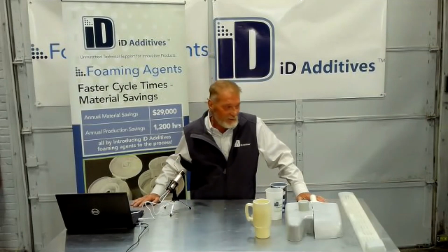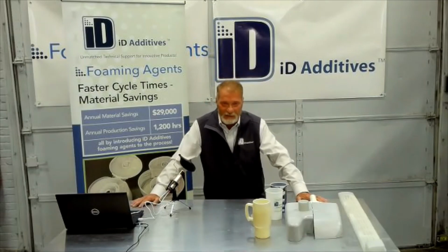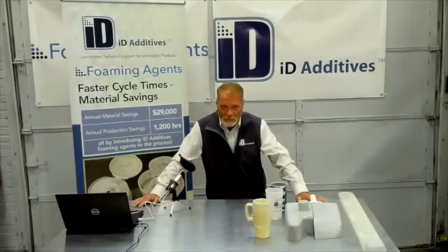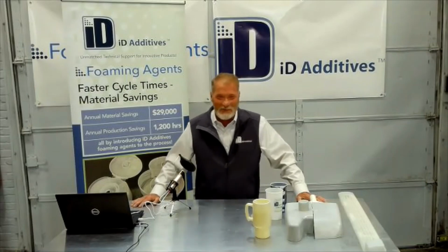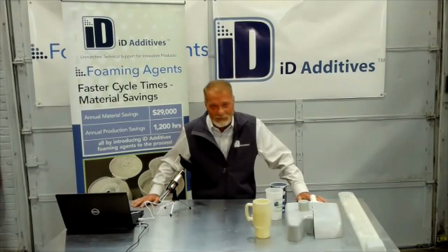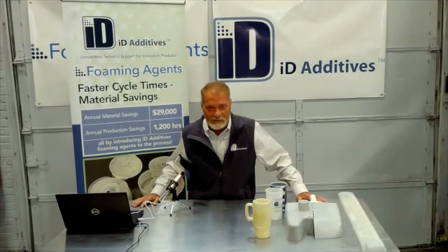What's nice about the combination of the two is, you know, the higher you go on fillers, the harder it pushes. But if you add foam, now it'll push easier, it'll fill easier, and you can take advantage of those temperatures. And I've dropped barrel temperatures off of machines that nobody wanted to see, but it sure worked out good after that. You know, they're a believer, but it took a while for them to come to grips with that viscosity change.